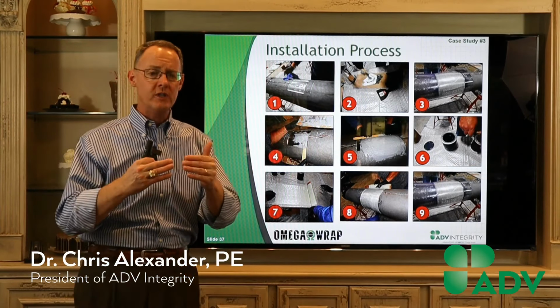On the right side, you can see we actually had a failure. It got to 3,700 PSI. So we almost got 1,000 PSI higher than we had to. And this is extremely thin. I mean, this is definitely less than 1/4 of an inch. So anyway, the good news is you check that box and you move on to the next step.